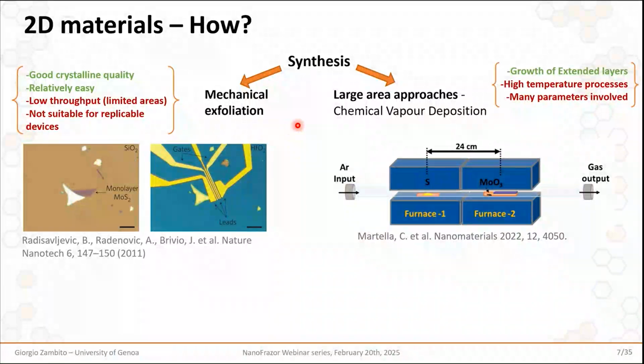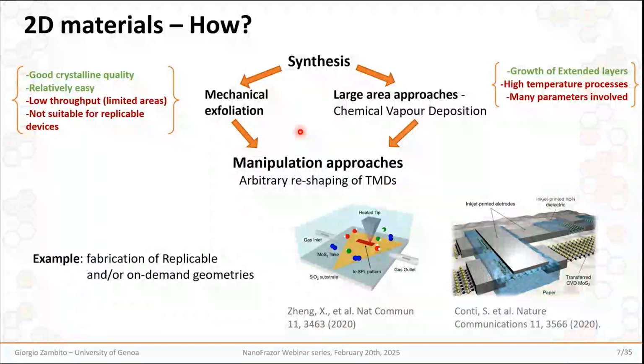And for these reasons, to overcome this limitation, people are making efforts to develop larger-area approaches, such as chemical vapor deposition. And these processes allow you to grow extended layers of materials such as transition metal dichalcogenides, but you have to involve high temperature processes, and there are many parameters involved in these kinds of processes, and it's even difficult to replicate these results from one facility to another, for example. But anyway, whether you choose to rely on mechanical exfoliation or on CVD approaches, then you are generally interested in manipulating transition metal dichalcogenides. For example, for achieving the ability to fabricate replicable and on-demand geometries.